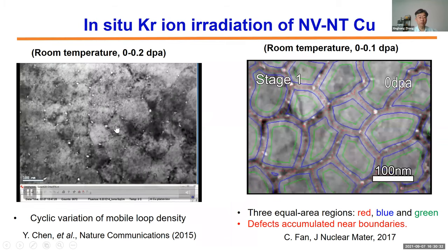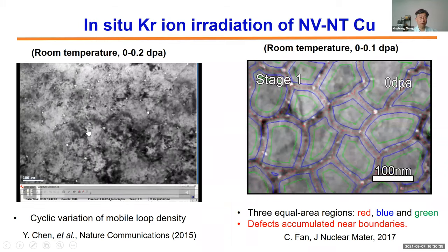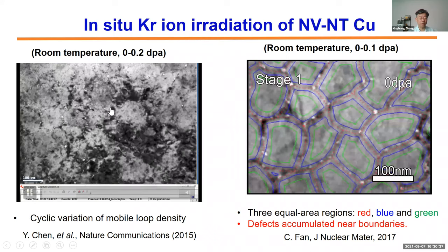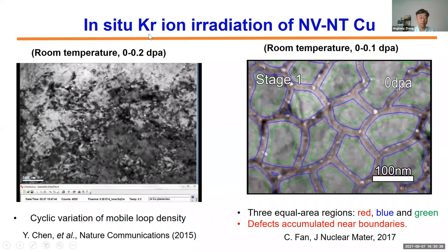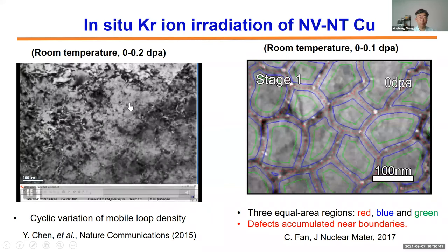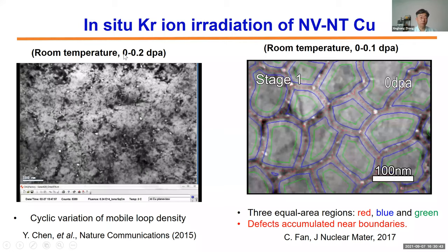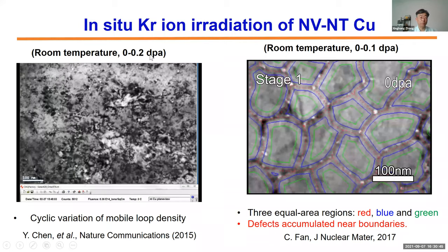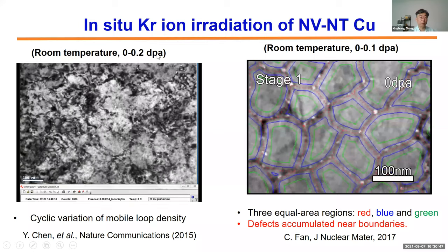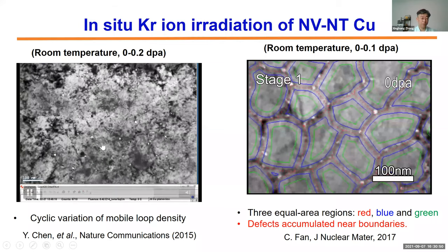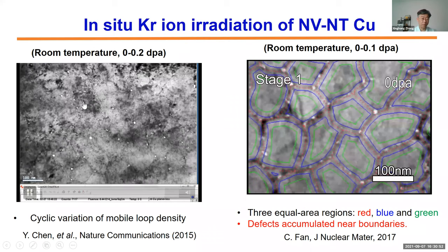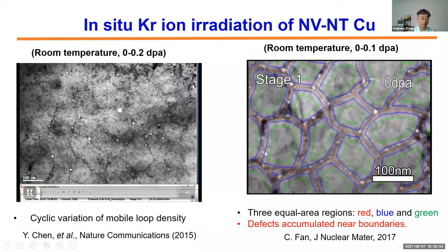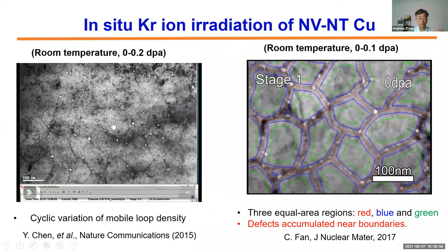So here is the in situ radiation at Argonne, IVEM, using TEM. We put in krypton ions during radiation, and this is at room temperature. The dose is low, 0.2 dpa, meaning displacement per atom. And you see a really complex contrast change, and these voids interact really rapidly with a lot of black dots, which are radiation-induced defect clusters. This was done by one of my former students, Yuxing Chen.